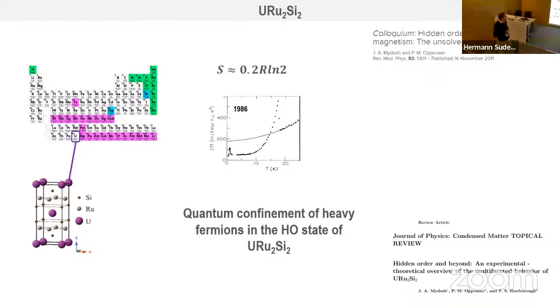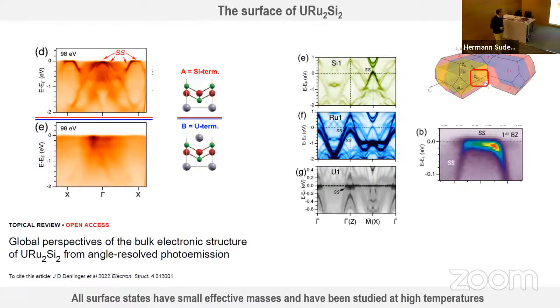We know something about this from long ago. And in spite of that, we of course know many things about the symmetry, many things about the excitations, but what actually is ordering there, we don't know. So this material is the one we studied for this, essentially because you have a nice surface. And let me, for completeness, show you also some photoemission results. Of course there is photoemission on the surface, and you get something which is close to a heavy surface state in some directions.